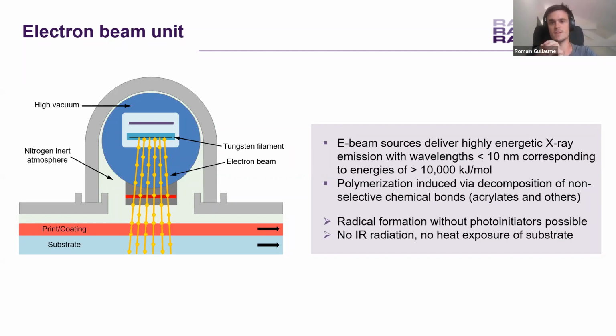Because of these wavelengths, the electron beam unit has to be built around an inerted atmosphere. So you can see that on the left drawing. It's needed in order not to absorb all of the photons. This kind of photons at 10 nanometers are highly reactive and mainly absorbed by the oxygen in the atmosphere. So for this kind of application, we need to inert the area around the generator, so the electron beam and the tungsten filament and the coating line.